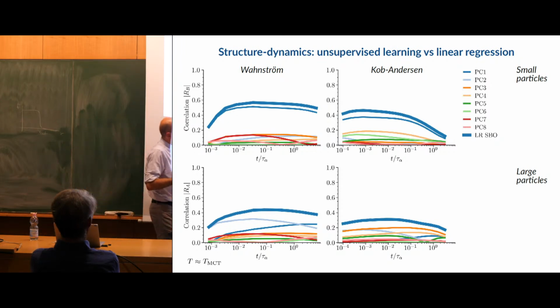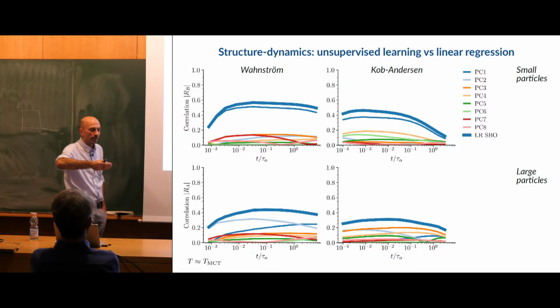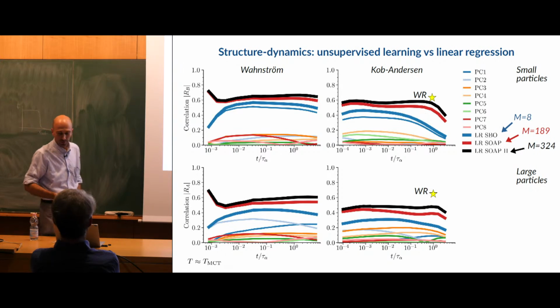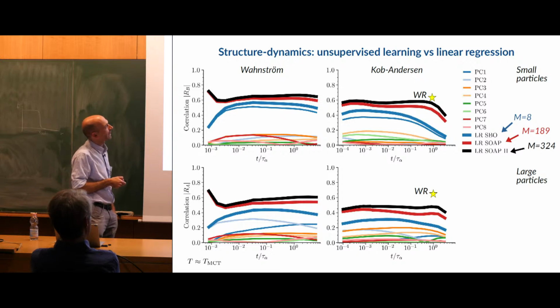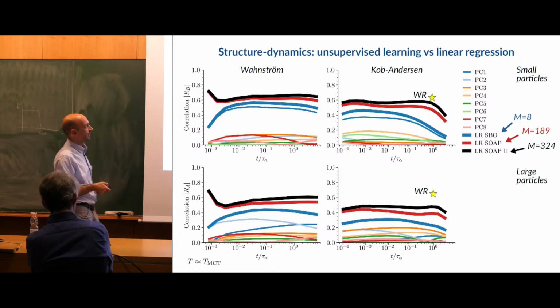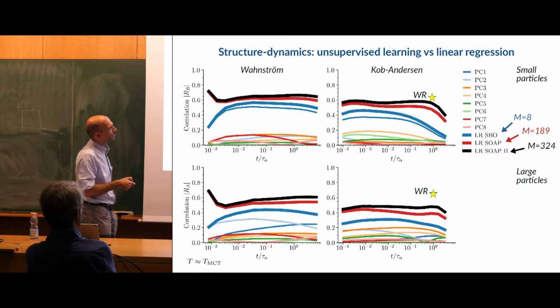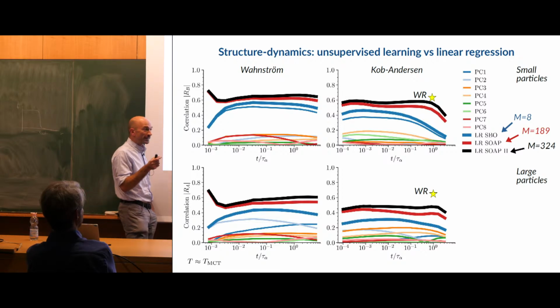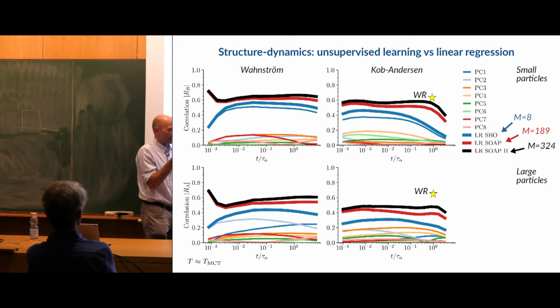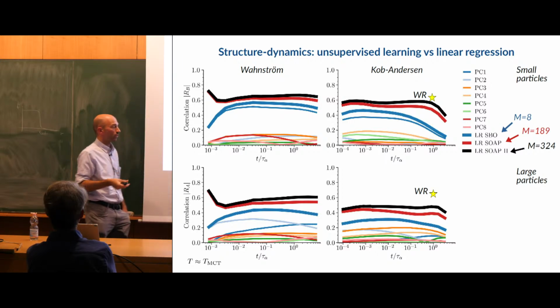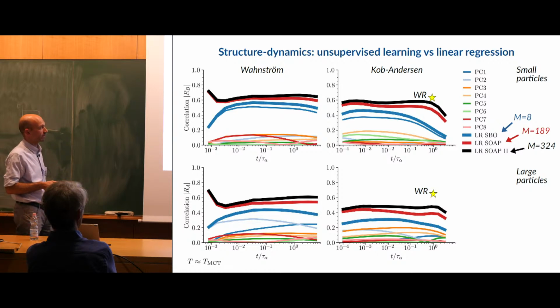Okay? Now, perhaps using higher dimensional descriptors, we get a better correlation. And so to check this, we use the SOAP parameters. And these are these new lines, red and black. So the red line is the SOAP parameters within the first coordination shell, okay, using one order of magnitude more features in this case. And as you can see, this really enables us to harvest more information, and we get a boost in the correlation almost everywhere, I would say, which means that even though there is no qualitatively new information in terms of the heterogeneity of the local structure, there is something that is relevant for fitting accurately the propensity of motion, which is indeed captured by these higher dimensional descriptors.